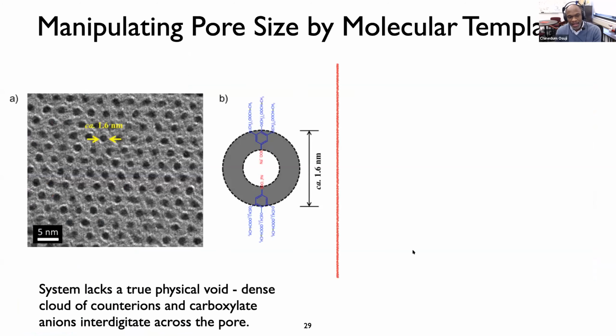But I digress. The interesting thing about those membranes, of course, is that those columns, in fact, do have 1 nanometer pores at the center of each column, but those pores are not true physical voids. They're filled by a dense cloud of sodium counterions, and the carboxylic acid head groups that are poking into that pore are not necessarily aligned. They're not necessarily registered as you go throughout the height of that pore.